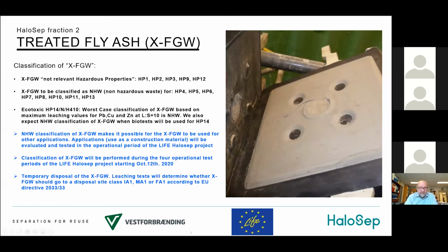In the meantime, we have to have a temporary disposal of the treated fly ash. And of course, leaching test will determine whether the treated fly ash should go to a disposal site, class inert waste, mineral waste, or hazardous waste, according to the EU legislation. Next, please.